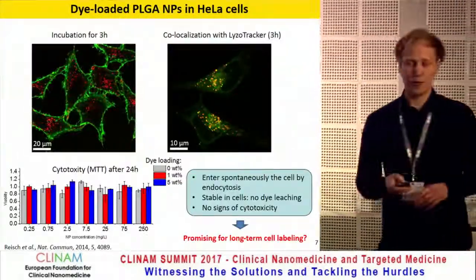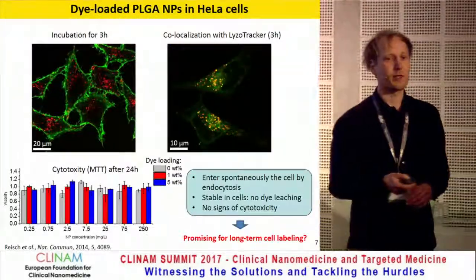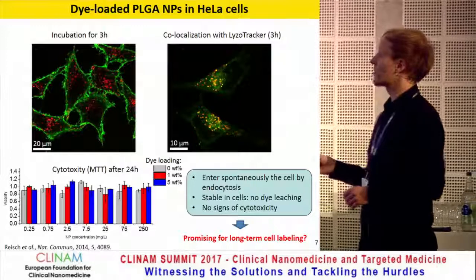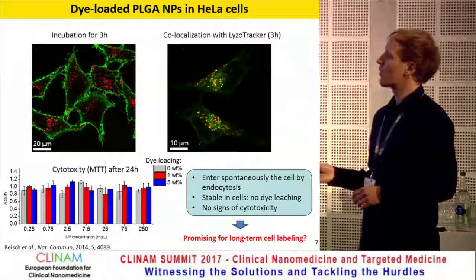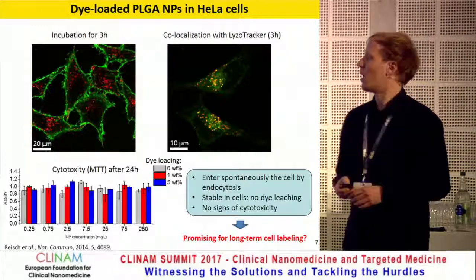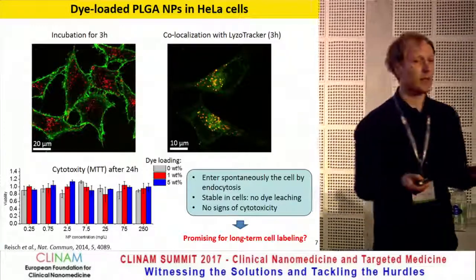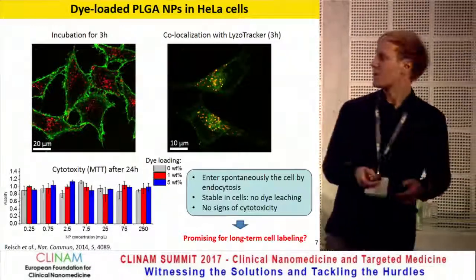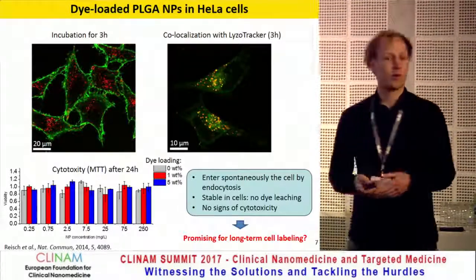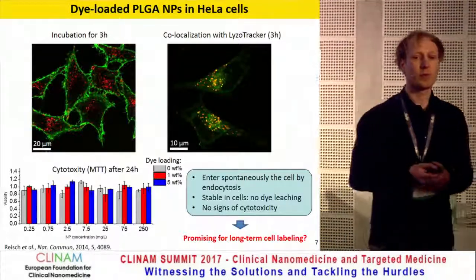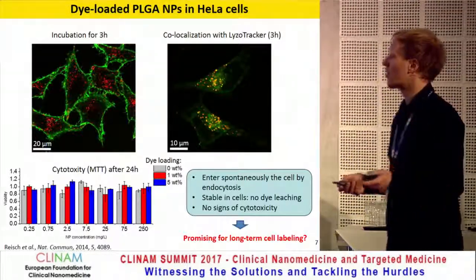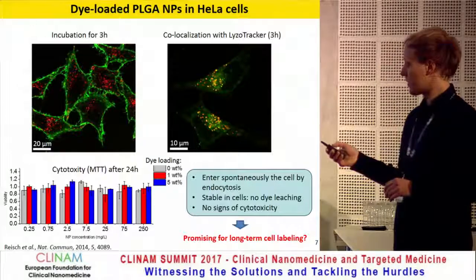These nanoparticles also internalize very nicely into cells and end up in lysosomes, showing very low cytotoxicity. We don't typically see any sign of dye leaching, so we thought that's quite promising, maybe even for long-term cell labeling.